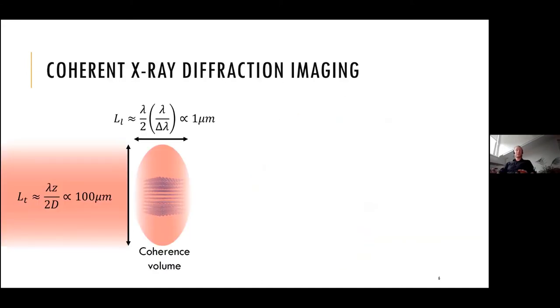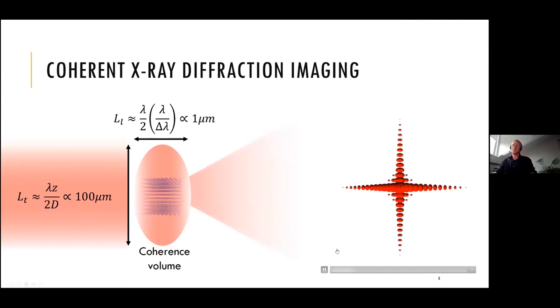Just a brief recap on the coherence. If we take an object, make it sufficiently small, and it's a crystalline object, and we put it into the so-called coherence volume, which is defined by the source parameters of the synchrotron, then the longitudinal coherence is defined through the monochromaticity of the radiation. For third generation synchrotrons, it's a value around 1 micrometer. The transverse coherence length is defined by how far we are from the source and how small the source is. By putting the object into this coherence volume, so we illuminate our object completely with a coherent beam, we can produce the coherent diffraction pattern, which in the case of the cubic structure will look like that.